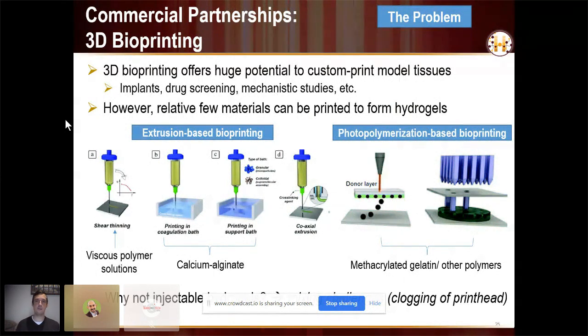Or you turn to photopolymerization. And again, for some cells, that's totally fine. But for other cells, you need to expose the cells to UV light, and particular wavelengths, or exposure over particular times, can be problematic. So injectable hydrogels are an obvious solution to this, but there's a huge problem in that mixing in a continuous process over a longer period of time with these gels is really challenging, because depending how you mix these things together, there's a very high risk of the print head clogging.